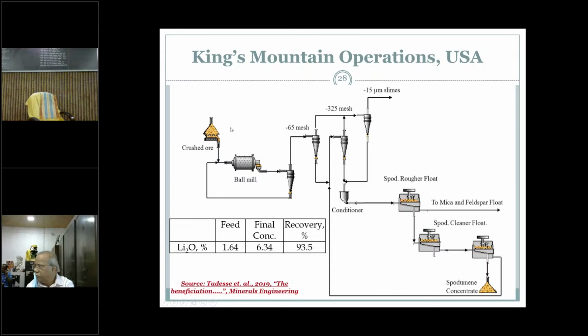They crush the ore and subject it to a ball mill, followed by classification, and the feed contains about 1.6% Li2O. The flotation cells are there. The hydrocyclone underflow will be subjected to rougher flotation followed by two-stage cleaners, and the cleaner concentrate will have about 6.3% Li2O, and the recovery of lithium values is around 93.5%.